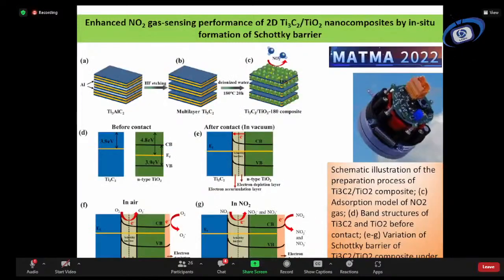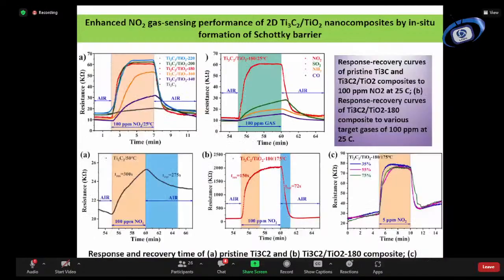We also simulated the conduction band and the energy band, and we also got the experimental band gap diagram from both sets of equations. So we also did the gas sensing. These are the gas sensing curves for the as-prepared material. You can see 180 or about 220, they show the maximum response for NO2 gas. And we have tested four gases: nitrogen dioxide, sulfur dioxide, NH3, and carbon monoxide.